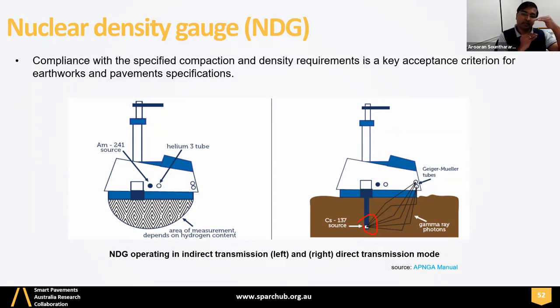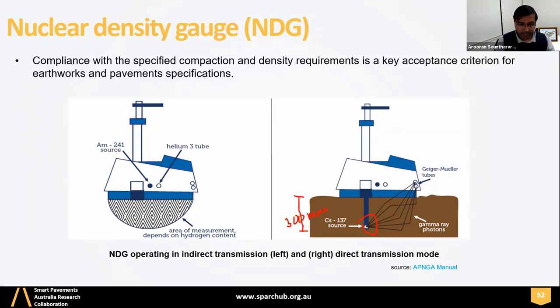The maximum depth that this NDG can go down is 300 millimeter. 300 millimeter depth can be tested with this NDG, right? And then once the test is started, the detectors in the gauge record the count rate of the radiation transmitted directly through the soil layer and display the wet density reading, right? So a more dense material absorbs more radiation, as we know already, resulting in the lower gamma count reading, which converts to the higher wet density.